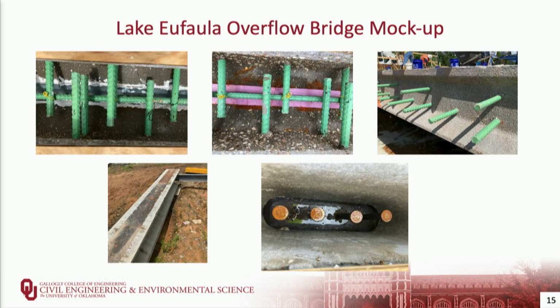Here you can see some close-ups of those connections in the mock-up. So they did a mock-up section close to the site so that the contractor could experiment with their methods, so that they could prove that they were able to make these specimens effectively, to place them on the bridge, and to make the connections with UHPC.